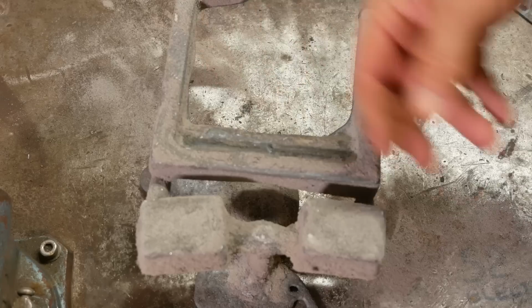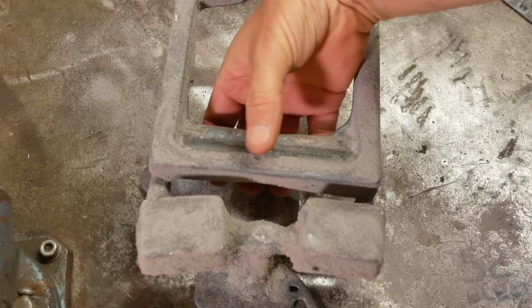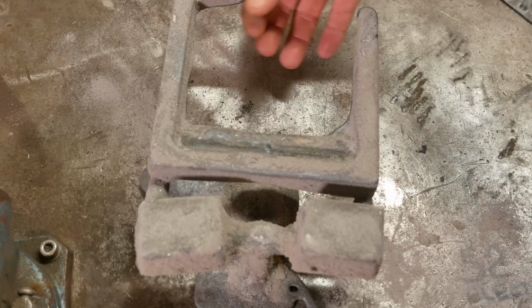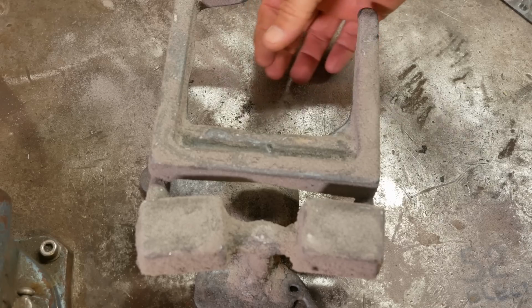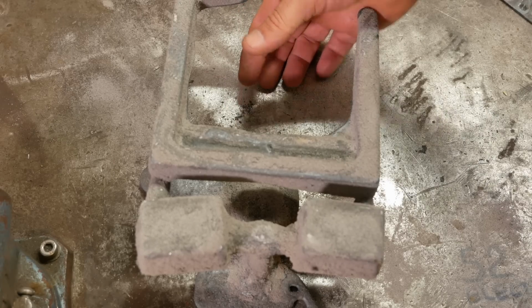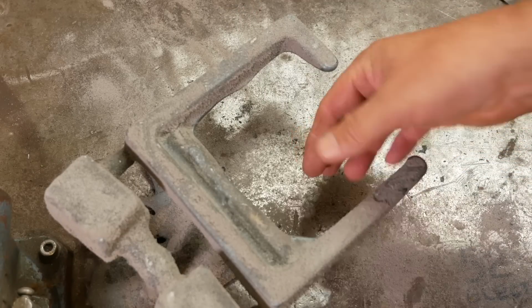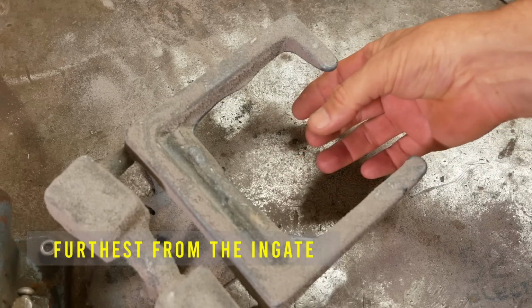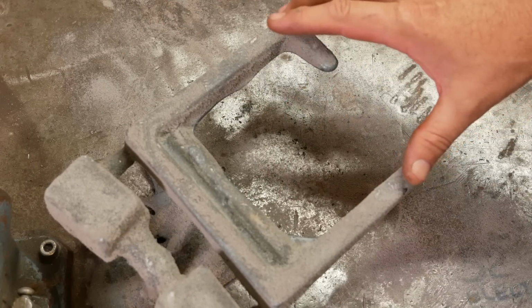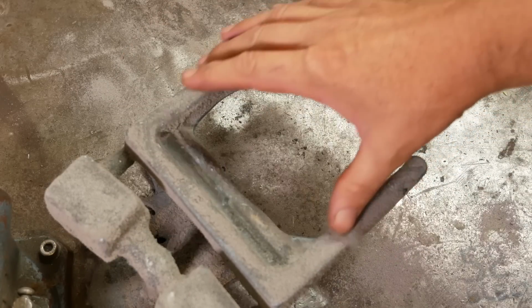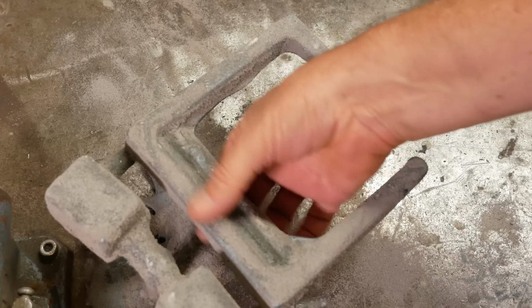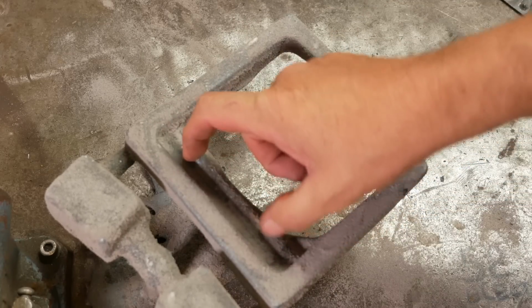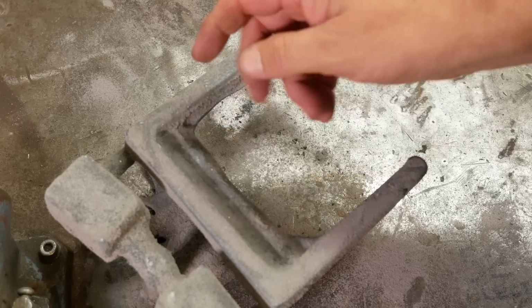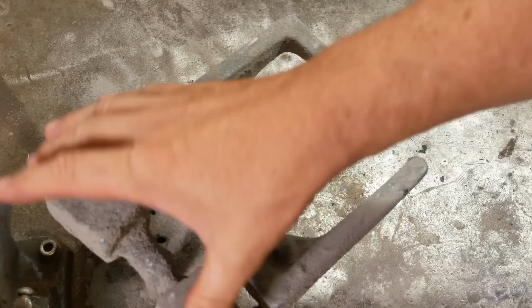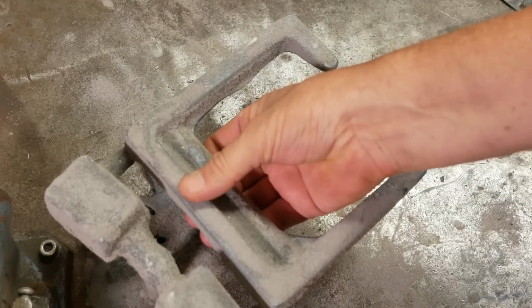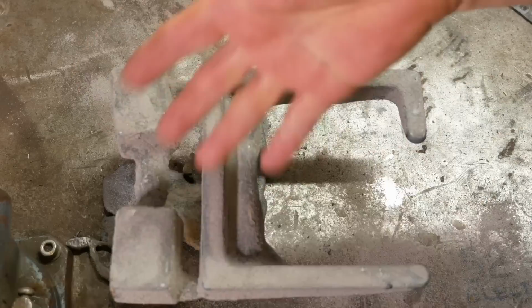This is the first one. This bottom part of this pattern is a very thick section, then the slightly thinner sections, and then at the top there's supposed to be a bit with the logo on it, which is the thinnest of all. So the idea would be the thinnest section is furthest away from the ingate, it will freeze first, and then the slightly thicker sections will freeze, and then these thick sections through here would be the last to freeze, and they would cause shrink defects. So I wanted these big shrink bobs to feed this section so that I wouldn't get shrink defects in the casting. The basic problem is the metal was too cold.